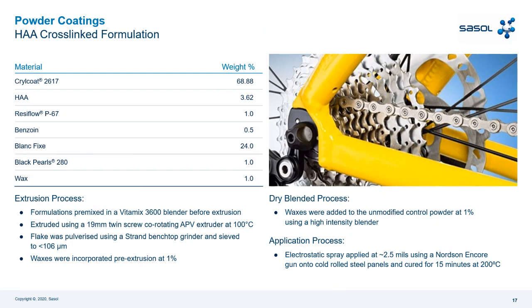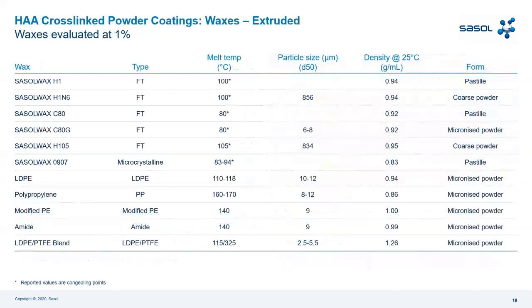The extrusion process is the same as before. The dry blended process is the same as before, and also the application process is the same. So 15 minutes in the oven at 200 degrees. This is the extruder wax that we use: Sasol Wax H1, H1N6, C80, C80G, H105, and the microcrystalline version Sasol Wax 0907.